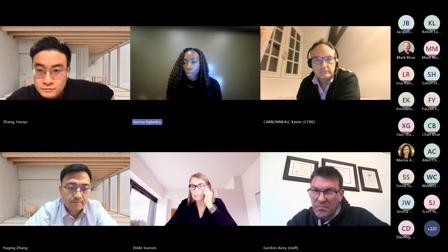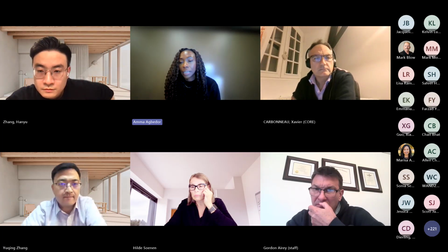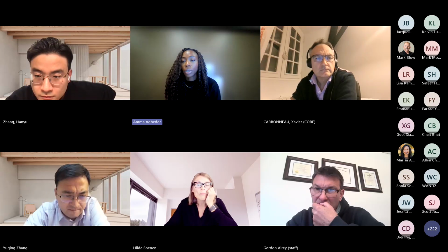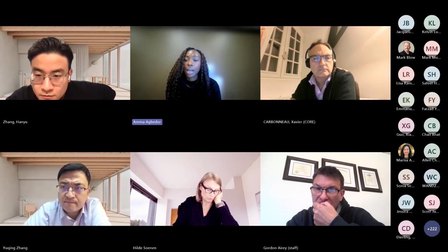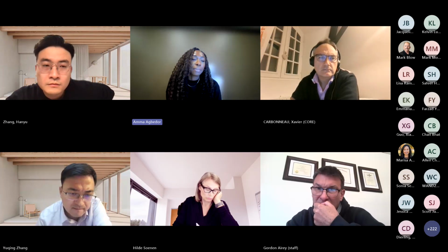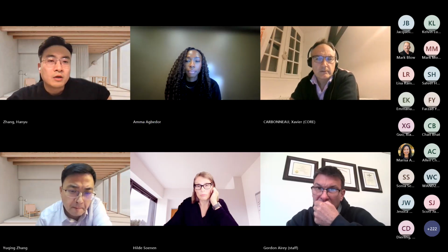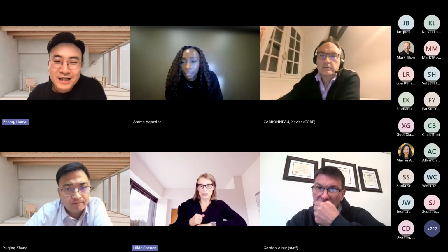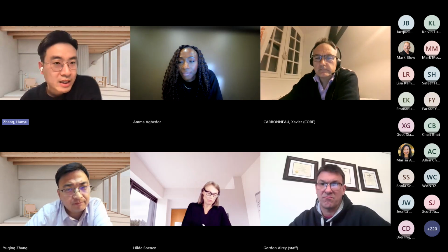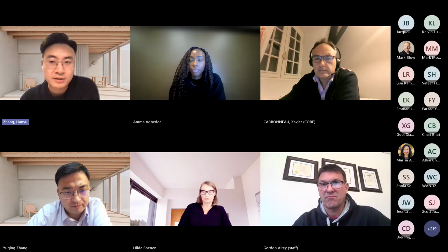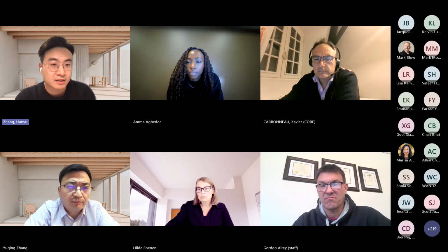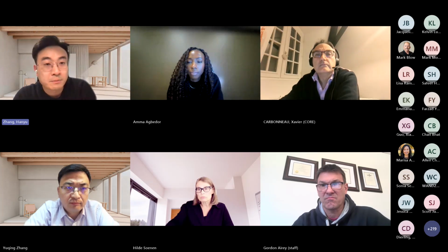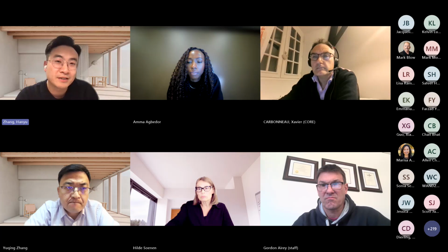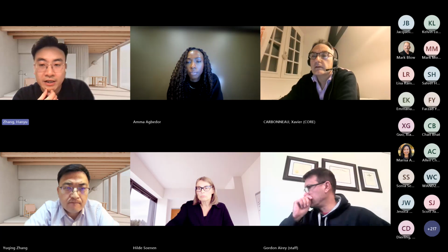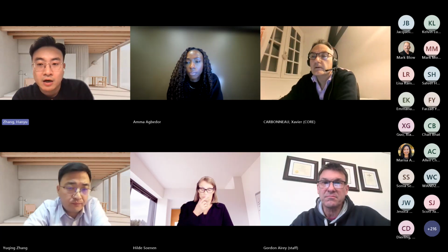There was a comment and question here: field aging will exhibit UV aging, which will contribute to the carbonyl index. How do you account for UV aging in the lab setting? Yeah, definitely. Especially in some areas, UV could be a dominating factor instead of only having oxidative agents. But for our case, the European cases, I don't think UV could be the major cause for the field aging. So that's why we still focus on the oxidative agents.